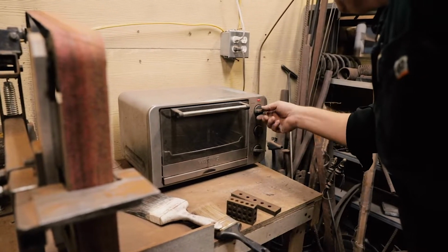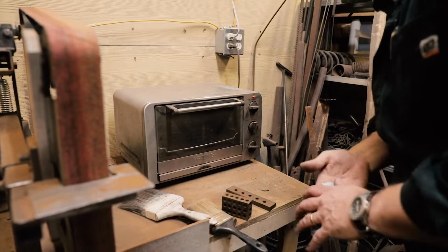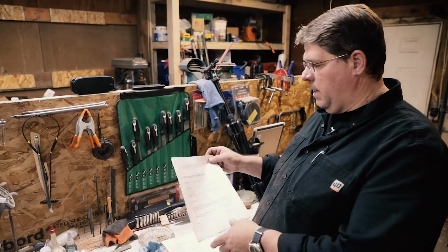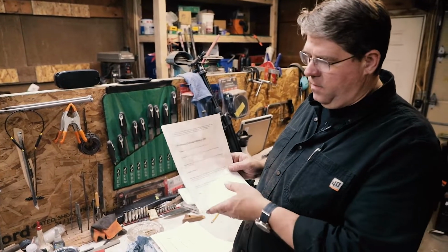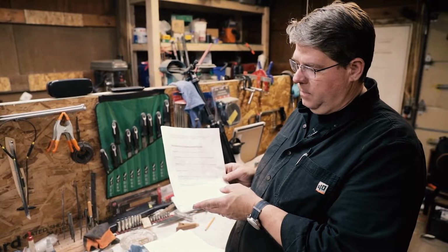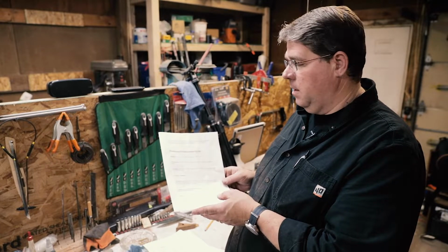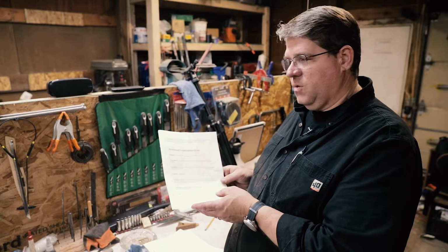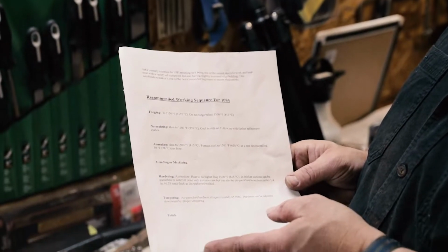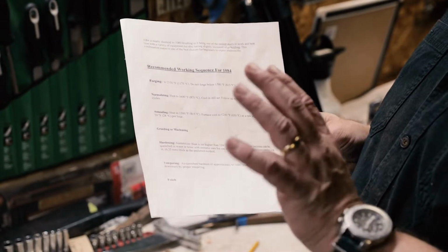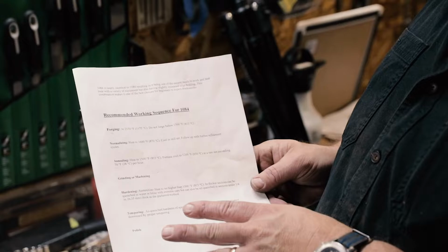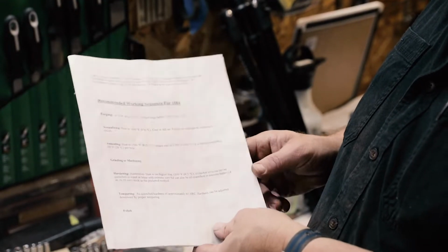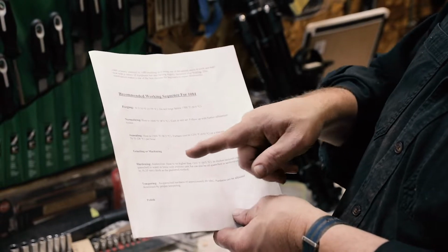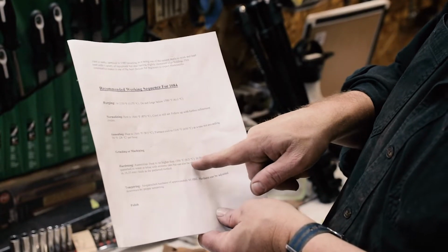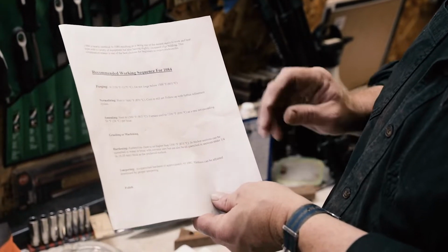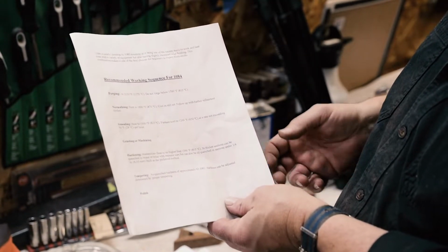That's at 450. Bake. All right. So the steel we're using is 1084, and this is a printout that I got from Kevin Cashen. Go to his webpage, and it gives you a great place to start. And since we're not trying to tailor this knife to any specific thing, we're just going to use the generalized average of data that he's compiled. So for hardening, to austenitize, we're looking at 1500 degrees, and it's generally accepted that you soak it for 10 minutes.